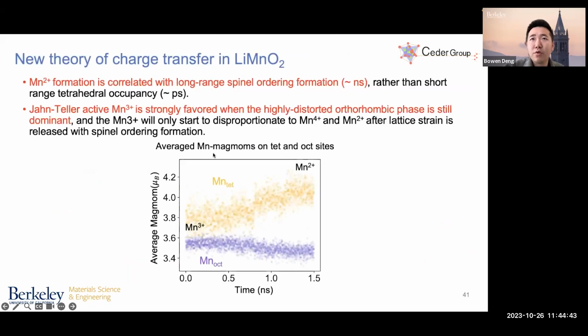So this observation actually leads to a new theory that we have discovered for this charge transfer and phase transformation in lithium manganese oxide material. In the plot showing this slide, we separate the octahedral manganese ions from the tetrahedral manganese ions by counting the number of oxygen bonds to the manganese. And what you can see is that over a 1 nanosecond time period, the octahedral manganese ions have a gradual decrease in their valence states, while the tetrahedral manganese ions have an increase in their valence states. Oh, sorry, have a decrease in their valence states.